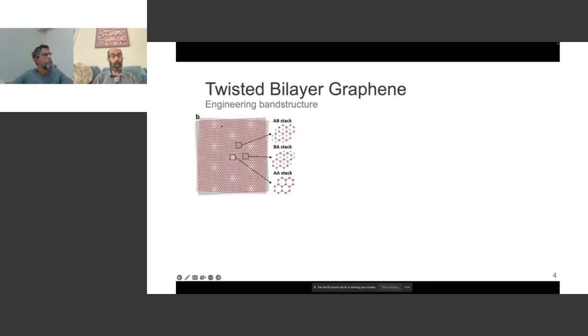And so these different appearing regions, one region is actually this very energetically unfavorable AA stacking, and then you have other regions that are BA or AB stacking, depending on which atoms in the first layer the second layer sits on top of. And this so-called moiré structure is analogous in real space to something that those of you who play musical instruments may be familiar with when you're trying to tune up your instrument. If two players are playing supposedly the same note, the same frequency of sound, but they're slightly off from each other, then what you hear is a sort of beat as the two sound waves go in and out of registry with each other. This is the same thing happening spatially instead of in time, and in two dimensions instead of in one.